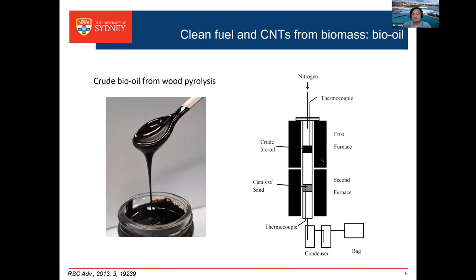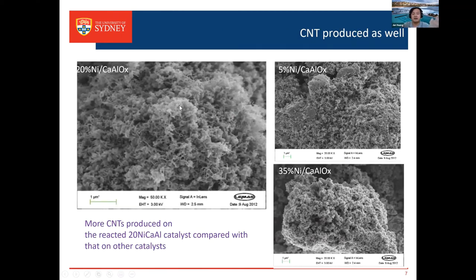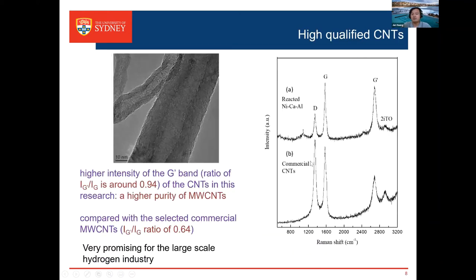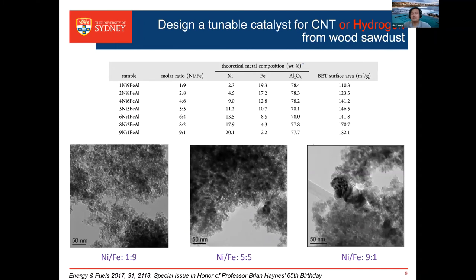So we developed this kind of process in the lab, and currently a pilot plant for it. First, we use a liquid, crude bio-oil, as a model reaction system. We pump it in, first do the pyrolysis, and then the catalytic reaction. Then we are able to split this hydrocarbon material. First, hydrogen comes out as a gas, and then the carbon grows on the catalyst surface to generate carbon fibers and carbon nanotubes. The quality of this multi-wall carbon nanotube is very good. Compared with the commercial one, the quality is higher based on the graphene ratio.